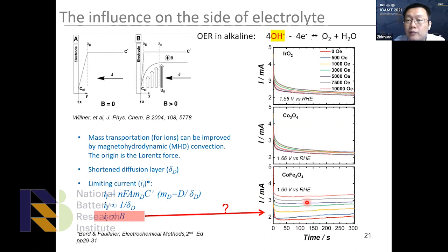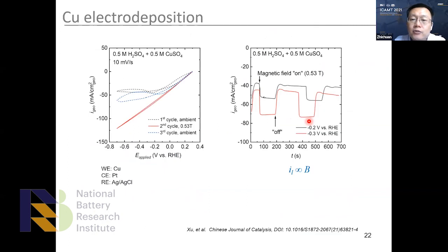However, it is not true, because if that were true, we should observe the same for all the other electrodes, for example iridium oxide and cobalt oxides, but we didn't observe that, right? And then we can do some other control experiment, for example, metal ion electrodeposition. We can apply the external magnetic field. So this is a very clear case.